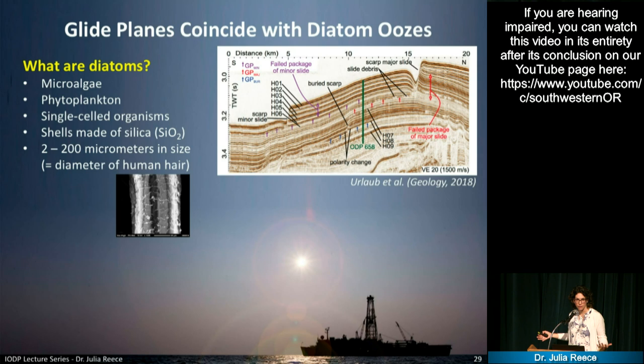So we can see lots of parallel reflectors, but what we also see are these step functions right here on the seafloor, and some further down that were buried at a later time. So these are indications for submarine landslides. And now what the scientists pointed out are these layers that are labeled H1 through H6. And these are layers that are extremely rich in diatoms. And diatoms are microfossils, so the remains of organisms that were very tiny single-celled organisms, phytoplankton. And it's made out of silica.